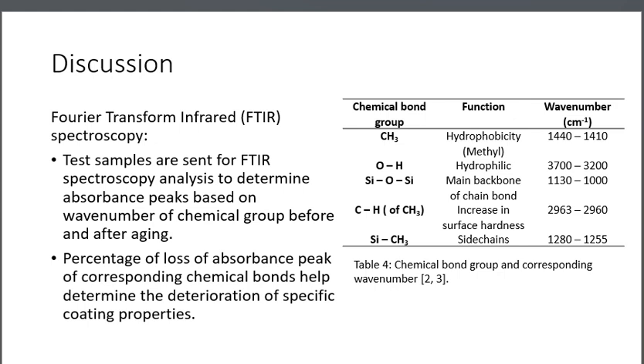To analyze chemical degradation, Fourier transform infrared spectroscopy was used. FTIR identifies chemical bond structure based on absorbance peaks at specific wave numbers. By comparing the absorbance peaks before and after aging, researchers can determine the percentage loss of chemical bonds, which indicates the extent of material degradation.